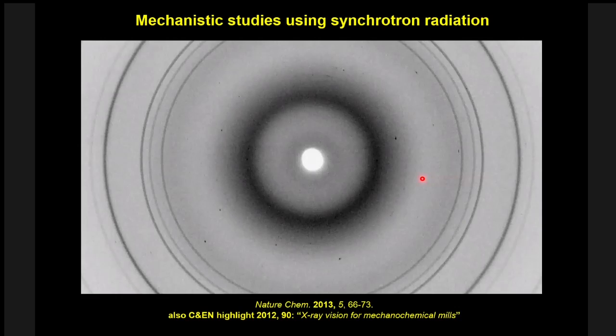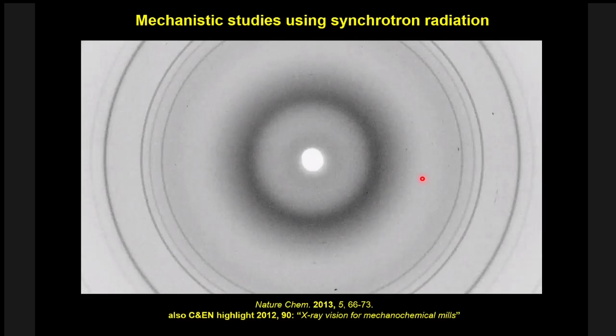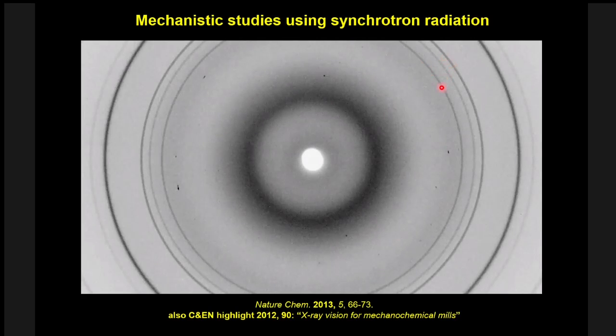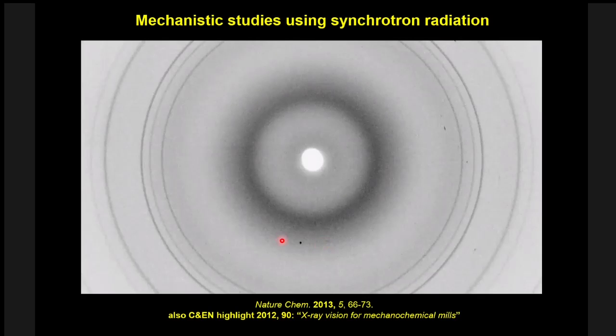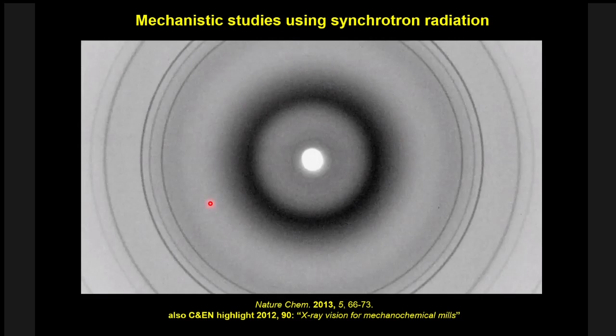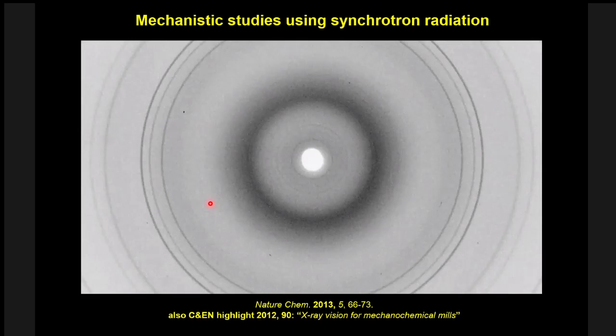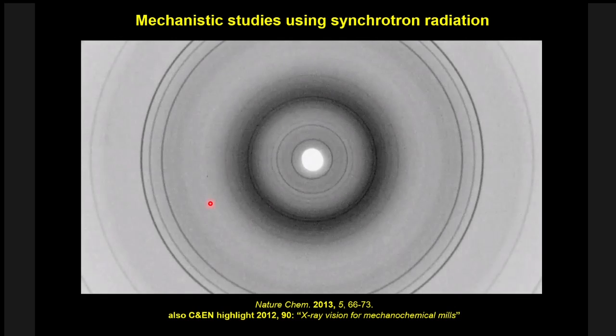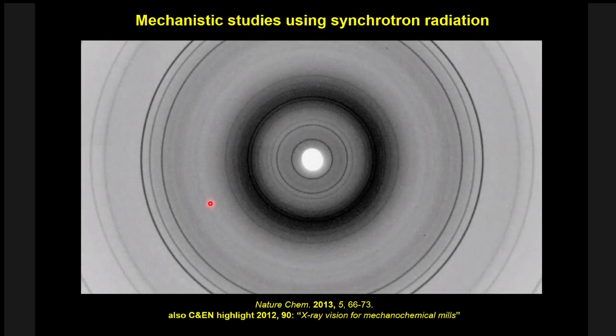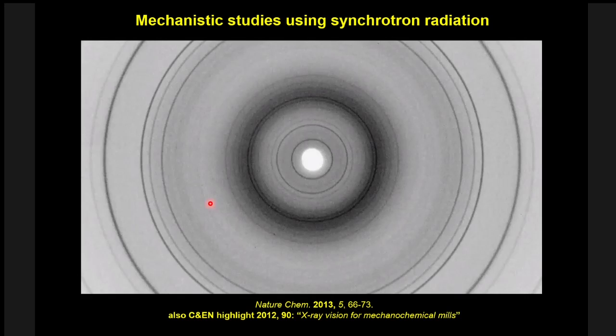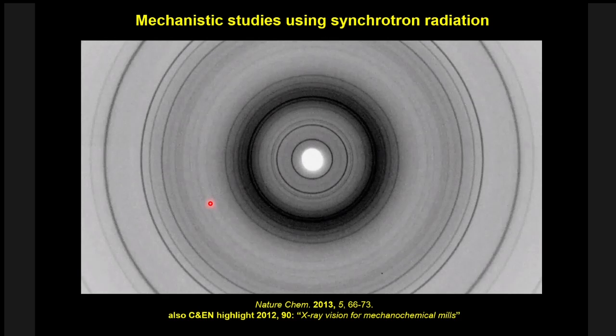So this is a powder X-ray diffraction movie of a mechanochemical process. These three lines, that's zinc oxide. The little spots here are those imidazole molecules, they're microcrystalline. And when you look at the middle of the screen, you will see these new rings appearing. These new rings are the signature, the structural signature of the nascent, in this case, product metal organic framework. And this really was the very first movie, the very first real-time in situ observation of what is structurally happening chemically inside the ball mill.